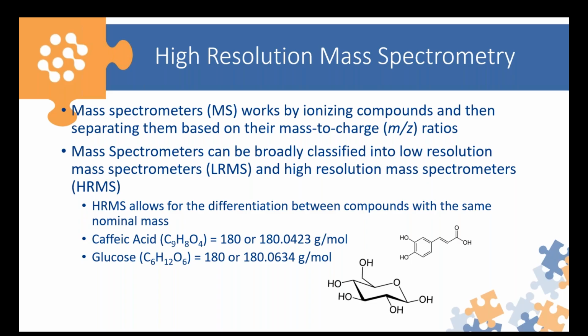And why is that beneficial? Well, this can allow for greater structural elucidation and differentiation between compounds, even with the same nominal mass. So just as an example, here on the slide, I have two very common compounds that are found in a lot of food products, and that's caffeic acid, a phenolic, and glucose, a carbohydrate. And they both have the same nominal mass of 180. However, if you extend that value to further decimal points, you can see they actually differ by about 0.02 grams per mole. And therefore, we could differentiate these two masses using high-resolution mass spectrometry.